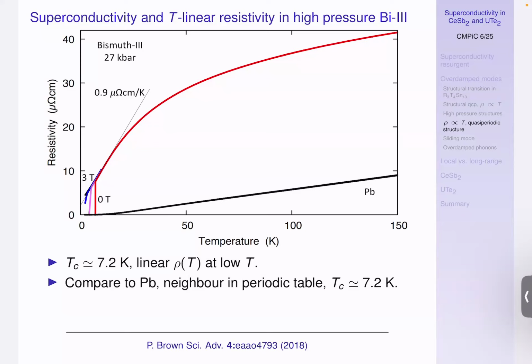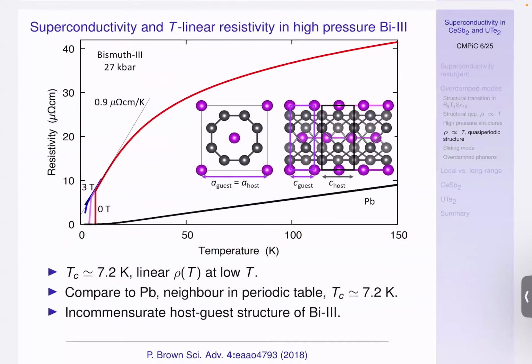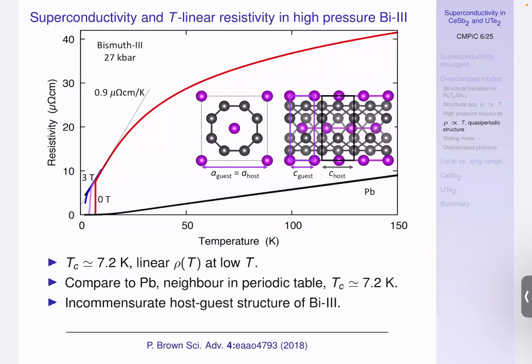Because the striking fact is that resistivity is linear in temperature, at least over some range, and also quite steep if you compare to lead, which is next door in the periodic table. So this is what resistivity of an elemental metal normally looks like. Right? And this is what you have in Bismuth-III. So Bismuth-III has a very curious structure.